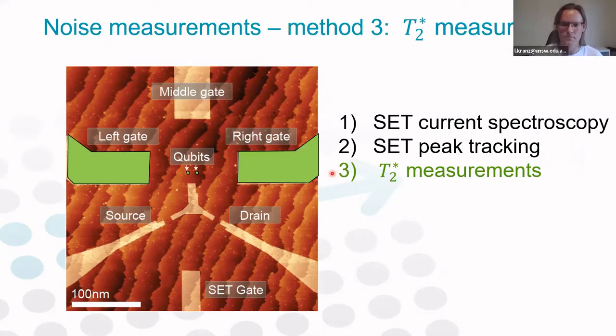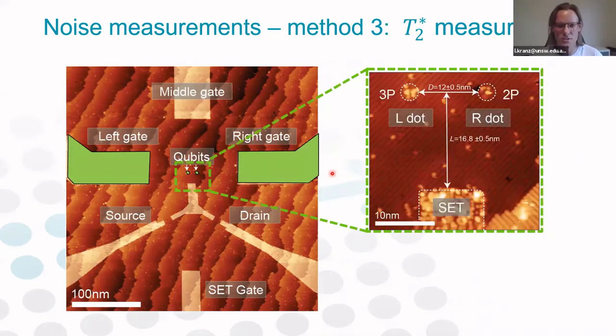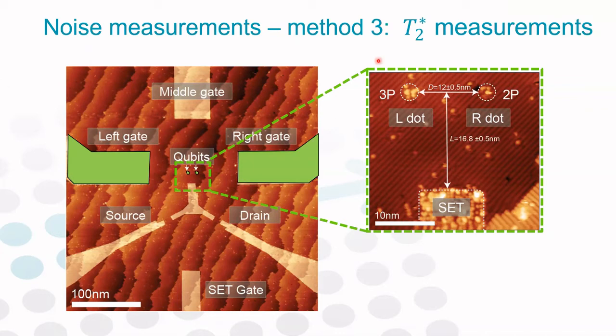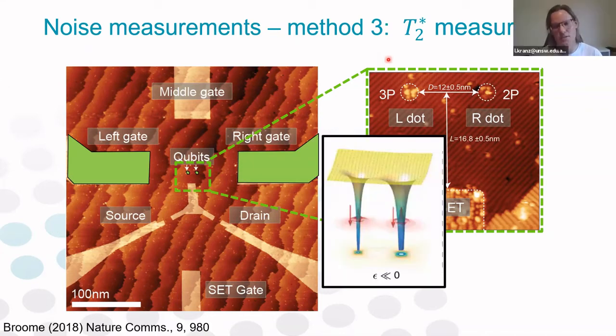If we zoom into this region here, we can see the top part of the SET and the 2 lithographic openings that host our qubits. By performing electronic measurements at cryogenic temperatures, we can characterize the device in terms of charging energies and relaxation times. Based on this information, we can determine the number of donors in each lithographic opening. In this case, we have 3 donors in the left dot and 2 donors in the right dot, and they are separated by 12 nanometers. We operate this device in the 1-1 charge configuration, which means we load 1 electron on each qubit.